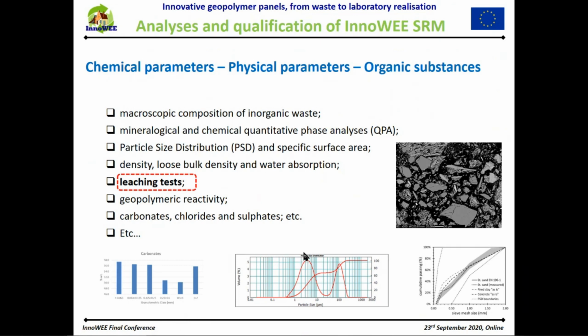To comply with the end-of-waste criteria set by local authorities, the obtained secondary raw materials are analyzed in the laboratory to verify that they meet the prescribed physical and chemical requirements, and specific procedures described in the standards were performed. For example, macroscopic composition of inorganic waste, mineralogical and chemical qualitative phase analysis, particle size distribution, density, water absorption, and leaching test. The leaching test was quite important because it's important to identify the heavy metals present in the waste, then geopolymeric reactivity and other analyses.